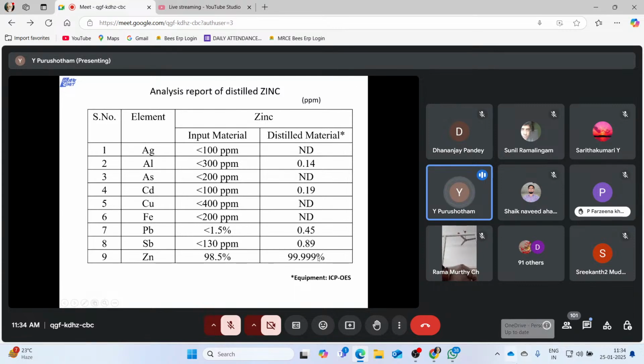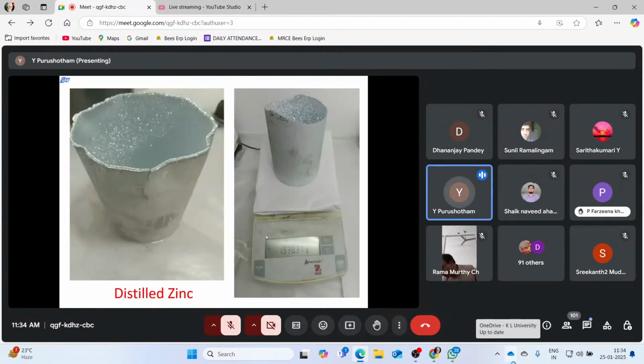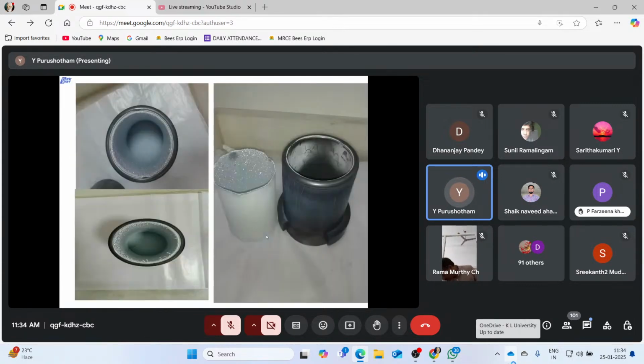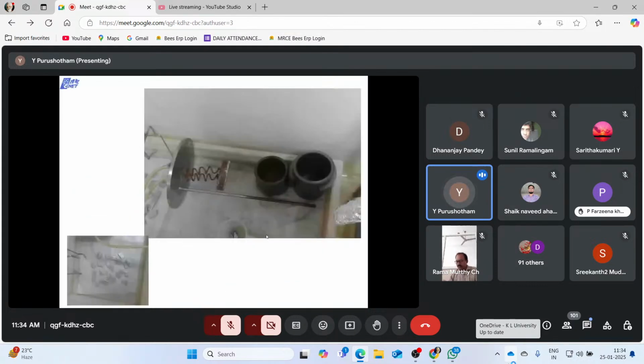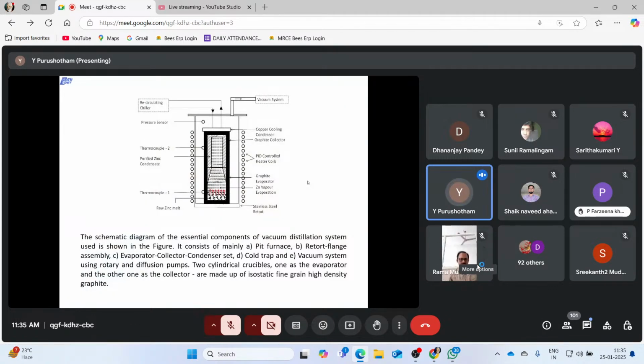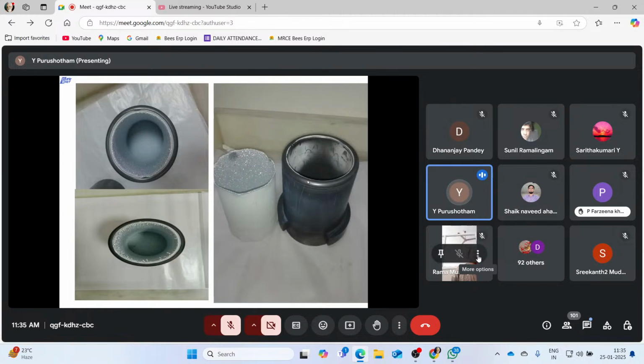The advantage of this vacuum distillation is that in this crucible you can load up to 5 kg of material. Whether 1 kg or 5 kg, the process time is also the same. So you can scale up to kg-level vacuum distillation, and you can get ultra high pure metals.